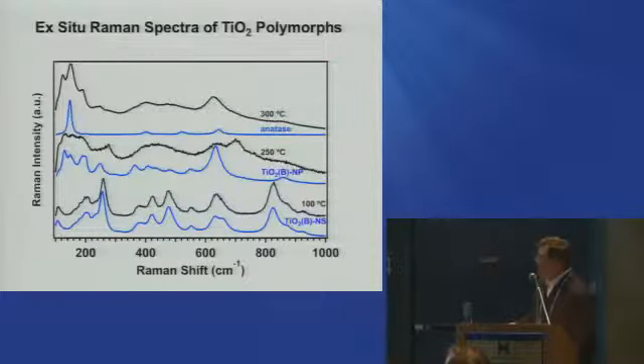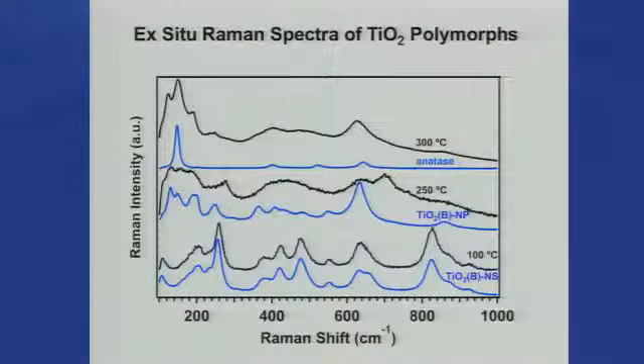Okay, the other thing that we were able to show, we were able to follow, is that when you actually make this material, you can heat it up and you can convert it into the anatase phase. And through using Raman spectroscopy, we could actually build a materials library and use the vibrational fingerprint to identify whether we had nanosheets, nanoparticles, or anatase.